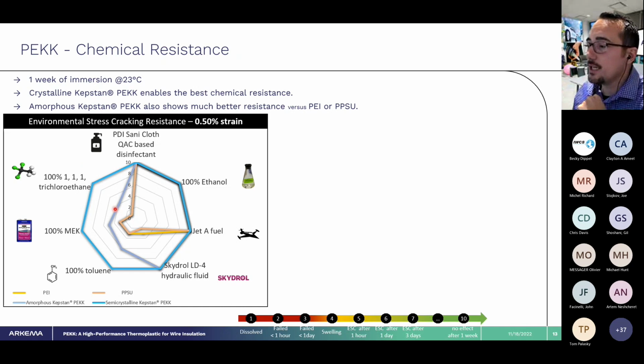What you can see is the brightish blue line is our semicrystalline or annealed PEKK, and it's essentially unaffected by all these chemicals, which is fantastic. Comparing that to PEI and PPSU, some of the chemicals that are attacking or essentially dissolving these materials do not affect semicrystalline PEKK. This is at a 0.50% strain.